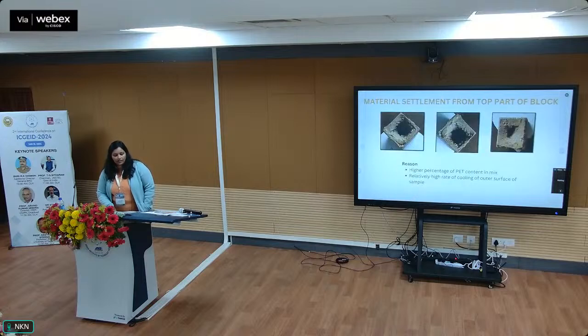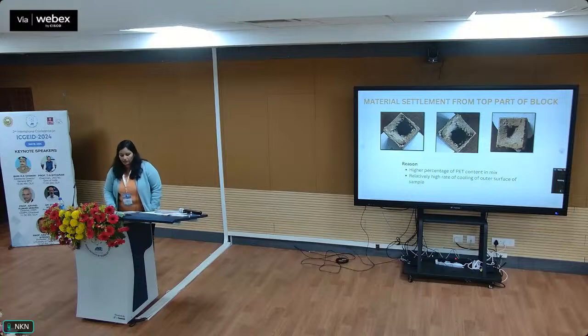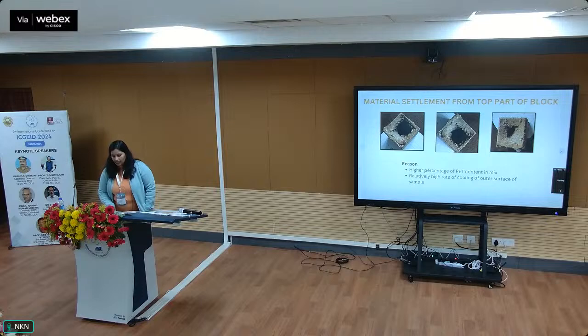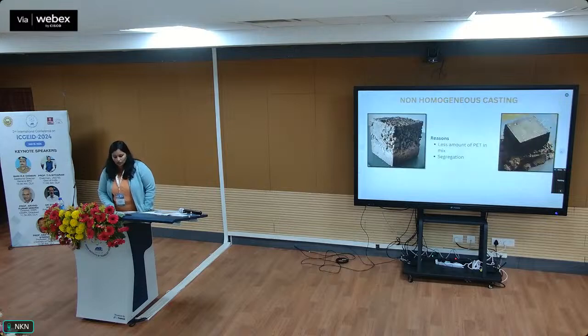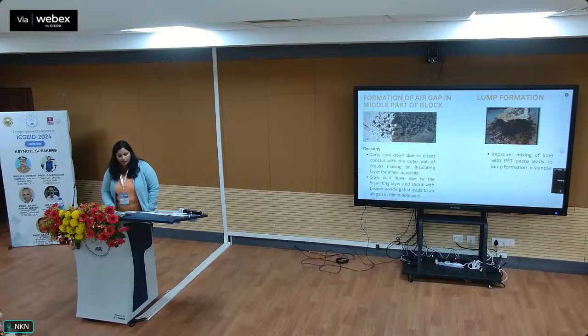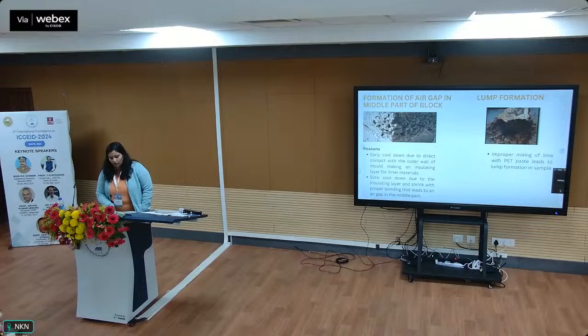The second problem we encountered is the material settlement from the top part. This is because of the higher percentage of the PET content, which I mean is around 60%. If we tried to exceed beyond 50%, the material started to settle down. Then non-homogeneous casting is basically because of the segregation and the lesser amount of PET in the mix. Then there was formation of an air gap in the middle part of the block. Lump formations were observed when we tried to add lime.